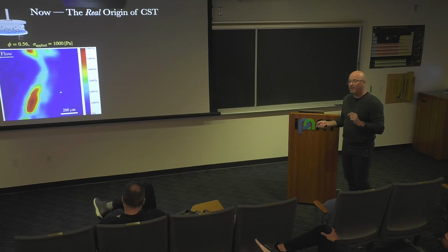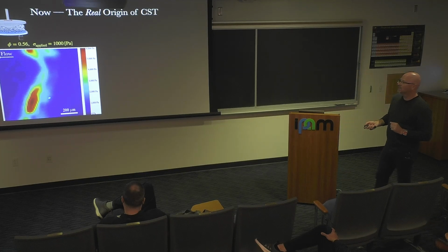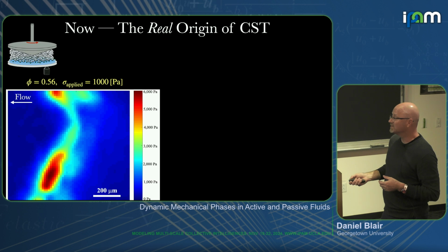So this is a precision experiment with a very messy system. And so as a consequence, we see that the size of these regions can be on the scale of 200 to 1,000 microns. And in fact, the scale of the stress locally can be very high, 6,000 pascals, 6 times the applied. And it's because I can average all of this. Newton's laws still exist.